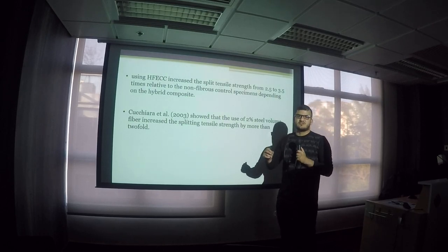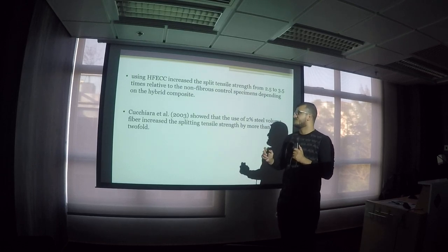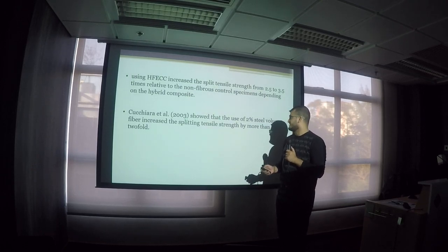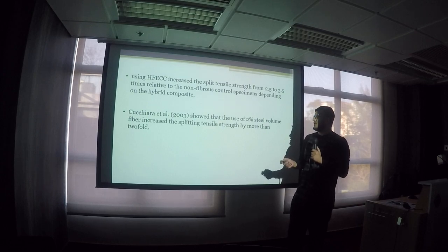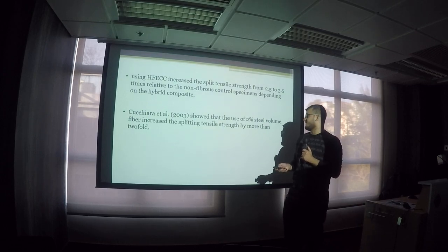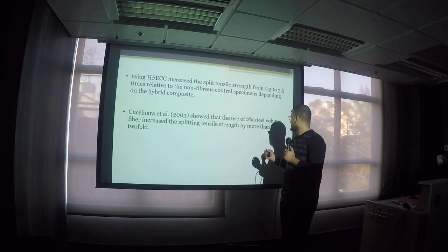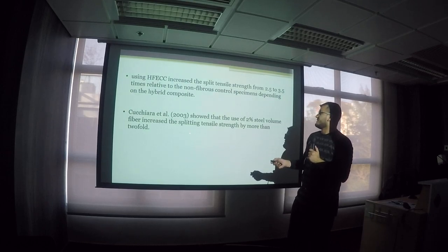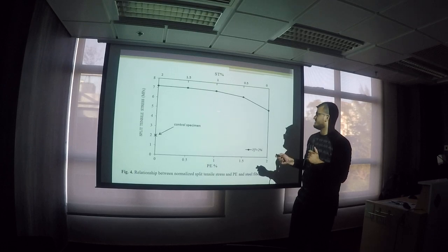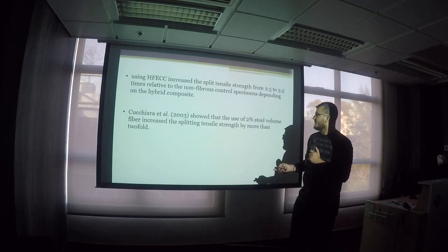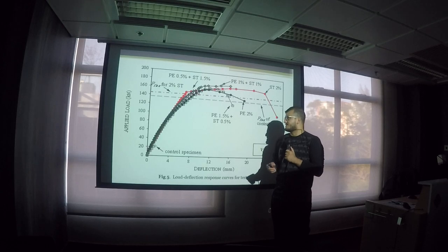And again, this result was inconsistent with previous research work, as you can see here. Cucchiara et al. in 2003 said that adding 2% steel may actually increase the split strength by twofold. It means 2 times, as you can see here. Okay, now let's jump into the response curve.